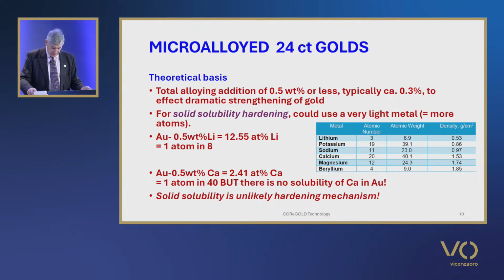In comparison, a gold 12.55 atomic percent lithium alloy is only 4.4% lithium in weight terms, which would increase hardness in the annealed condition to about 40 Vickers and to about 80 in the cold work condition. So maybe a gold lithium alloy could provide some of the necessary property improvement by solid solution hardening.